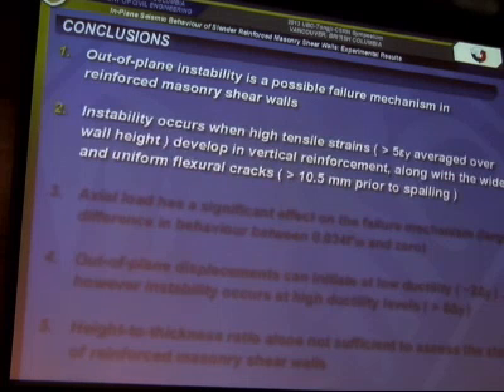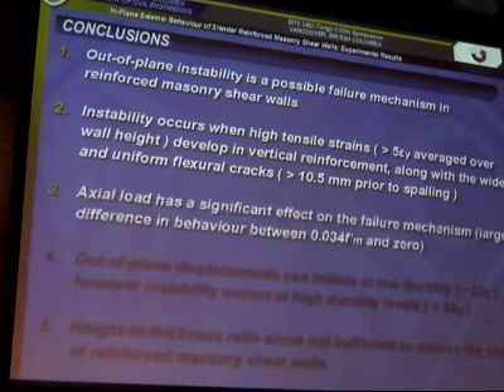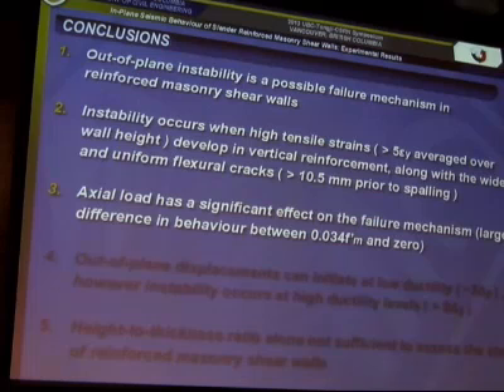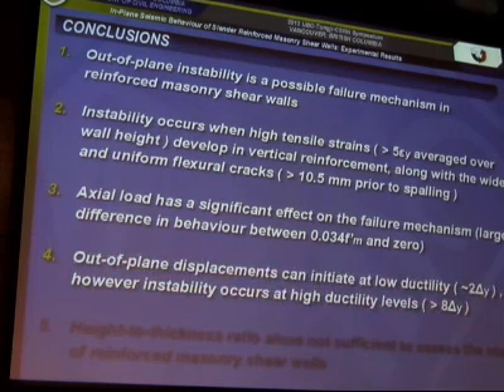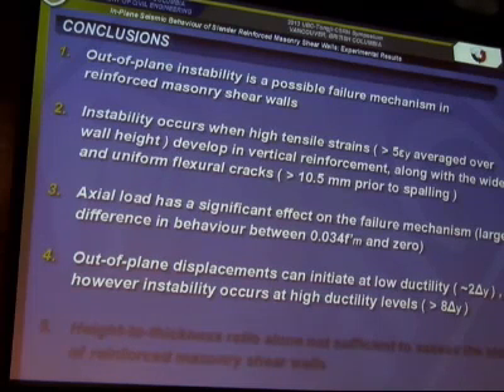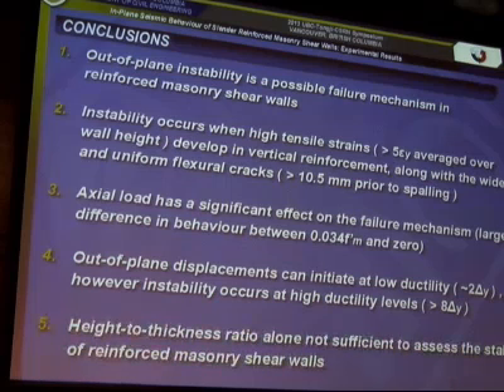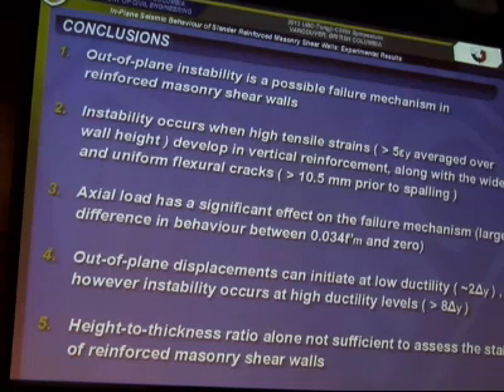So our conclusions are that out-of-plane instability is a possible failure mechanism in reinforced masonry shear walls, and that instability occurs at very high tensile strains, but it must occur over wide and uniform flexural cracks. The applied axial load apparently does have a quite significant effect on the failure mechanism, and out-of-plane displacements initiate at low ductility levels, but they do not become critical until later on. And it is also quite apparent that the height-to-thickness ratio in itself is not sufficient to assess the stability of reinforced masonry shear walls.